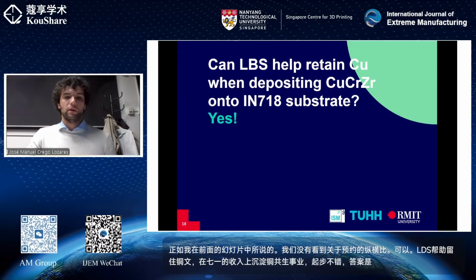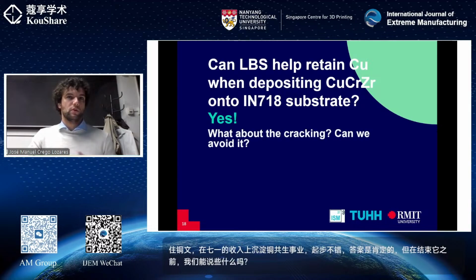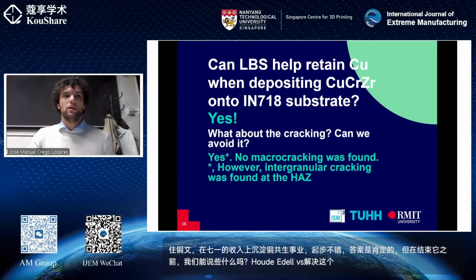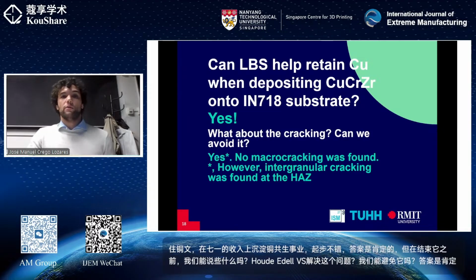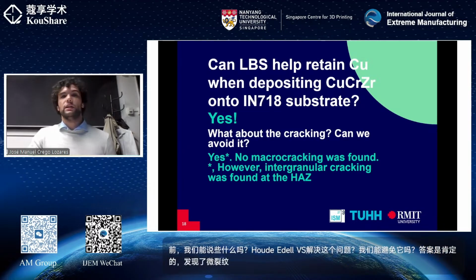But before wrapping it up, can we say anything about the cracking? How did LBS address this matter? Can we avoid it? Well, the answer is yes. No macro cracking was found. However, intergranular cracking was found at the heat affected zone.